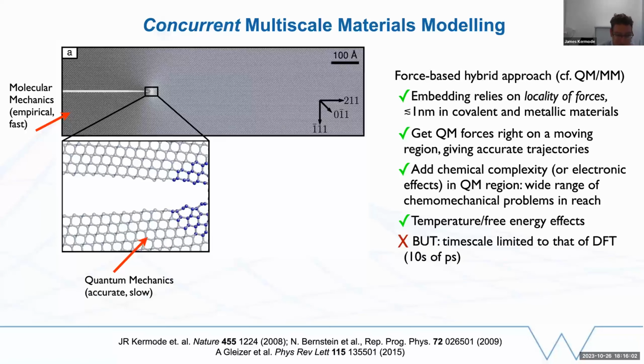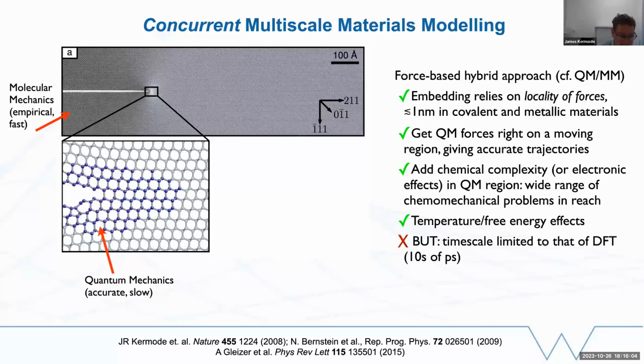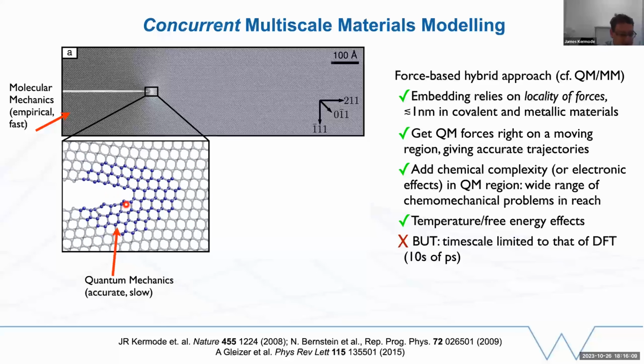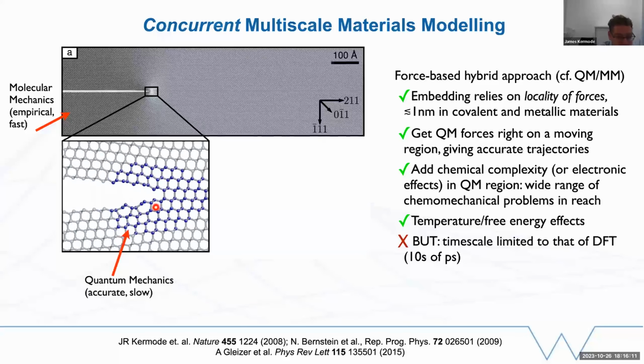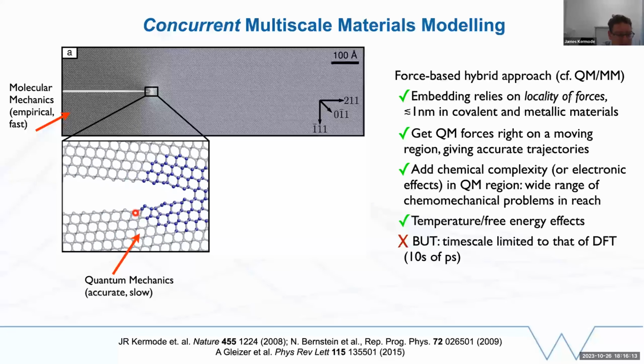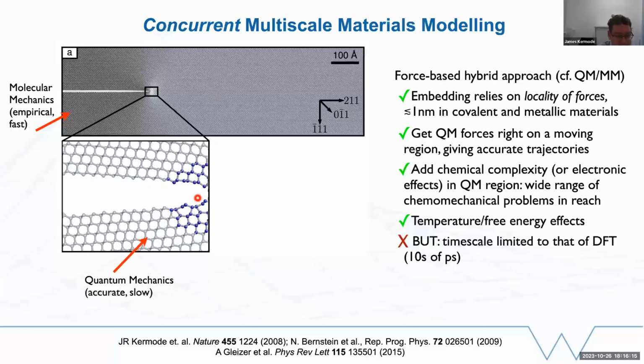And actually, it's even nicer than that. If we look carefully at the fracture surface, you see some reconstructions of the surface that are due to electronic effects. So we have an alternating chain of 5 and 7 membered rings here that's caused by delocalization of pi bonded electrons along this surface. So the DFT is really putting in extra information. We don't have to train or parameterize that on anything, and we can move to new systems rapidly.